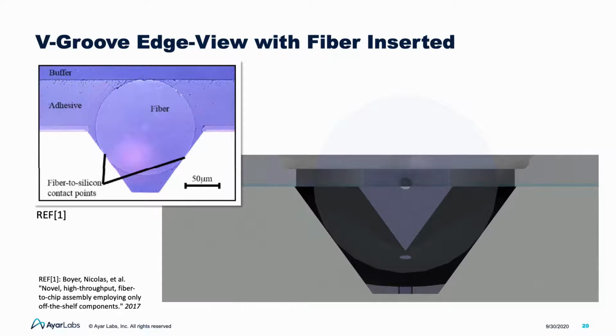Finally, note that while the die is hermetic, as all CMOS die are, the epoxy is exposed to environmental stress. For example, epoxy must perform under highly accelerated stress testing, HAST, temperature humidity bias, THB, temp cycling, and moisture sensitivity level testing. Ideally, the epoxy will not hygroscopically swell, since the fiber must be precisely held in position relative to the spot size converter. These are some of the general examples of material properties that should be considered for fiber attach applications.